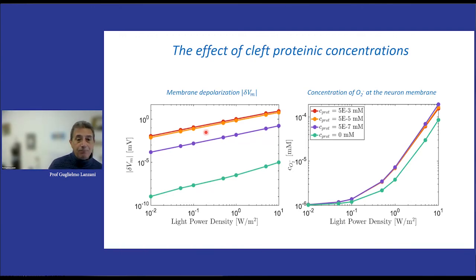So you can gain several orders of magnitude increasing the protein concentration, but just by two orders of magnitude. And in particular, in this range of the optical application, you see that you can reach almost 1 millivolt depolarization for one nanoparticle if there are proteins in the cleft. So to sum up, if there is this highly resistive cleft, then the electrostatic effect is very efficient.